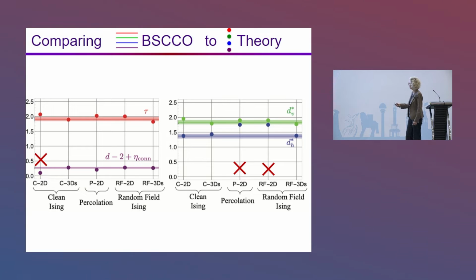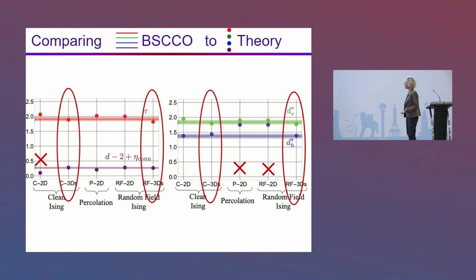And so this right here, the volume fractal dimension is actually pretty far off as well. The random field 2D Ising model is off as well. The hull fractal dimension in that case is not matching. So we've ruled out a few models with this analysis. What's left is the 3D models, actually. So this analysis isn't enough to distinguish for us between the clean 3D Ising model or the random field 3D Ising model.